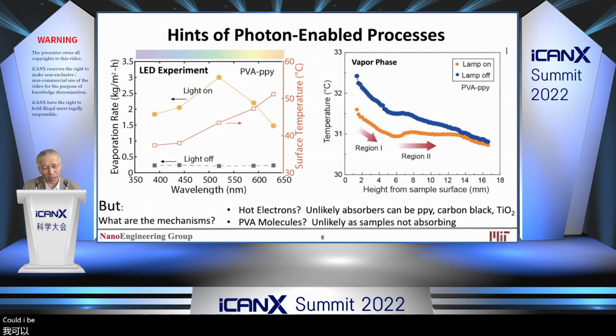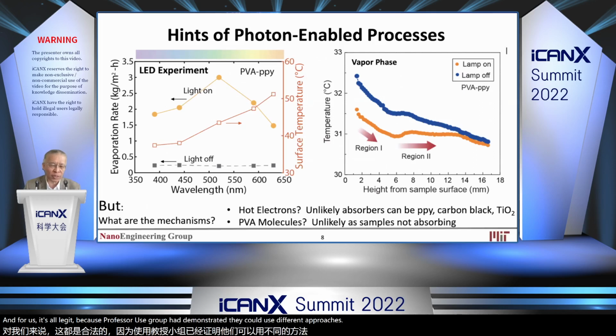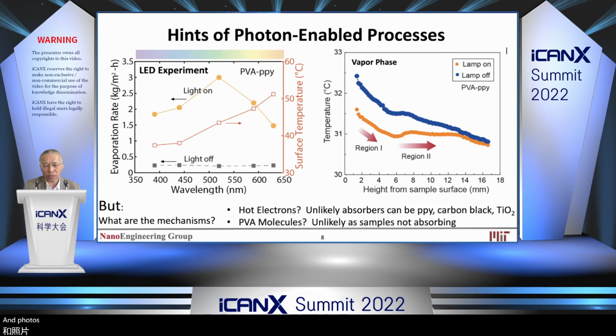Could that be hot electrons? Could it be the PVA molecule? And for us, it's all negative, because Professor Yu's group had demonstrated they could use different absorbing materials and they could all get a similar effect. It can't be hot electrons, since you have different absorbers like titanium dioxide, polypyrrole polymers, and even graphite. And what about the molecule itself? This is polyvinyl alcohol, and we know the material does not absorb in the green. So we were at a loss. We didn't know what was happening.